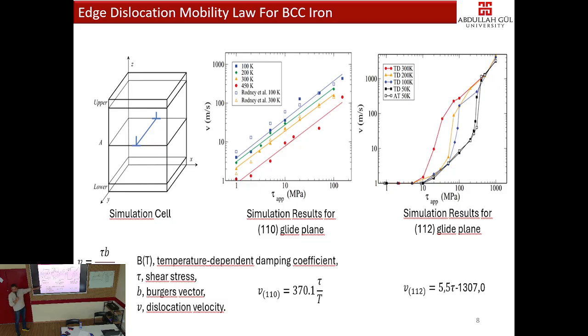Tau is shear stress, b is Burgers vector, B is drag coefficient. And the drag coefficient is only a function of temperature. So depending on the temperature, if you get the slope, you can find the B very easily. So this is only for 110 plane. For 112 plane, it is more complicated.